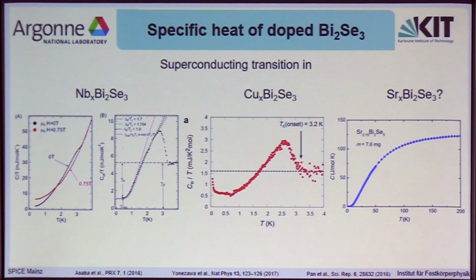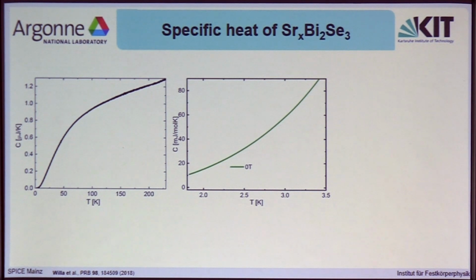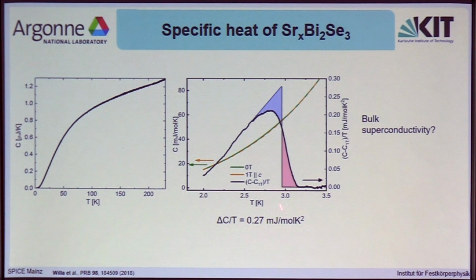So we set out to measure this compound, and you can see here the first measurement that we conducted on the left-hand side, a cool down from room temperature, and then a zoom in into the superconducting region. And as you can clearly see here, I guess there is not much superconductivity to be seen. It took us a few samples to realize, but if you actually measure the 1 Tesla curve, which suppresses superconductivity and makes the sample normal, and then you take the difference, due to the high resolution capability of our setup, we were actually able to resolve the superconducting heat jump in the sample, which is less than 0.5% of the specific heat at that temperature, or 0.27 millijoule per mole Kelvin squared.